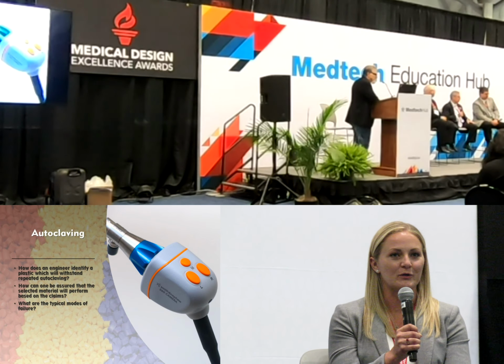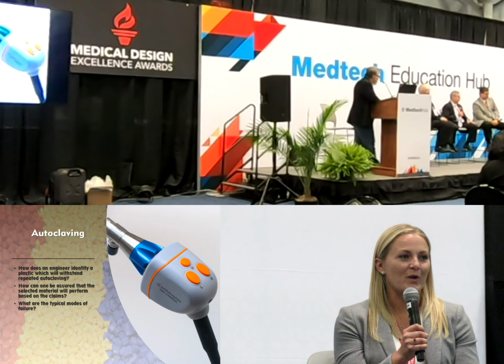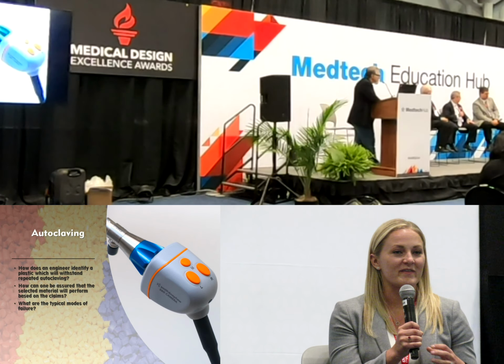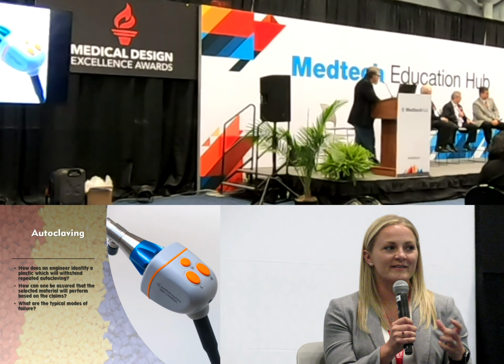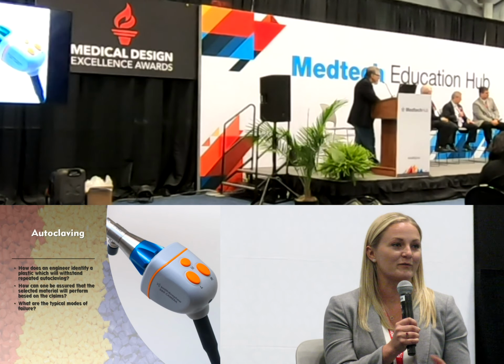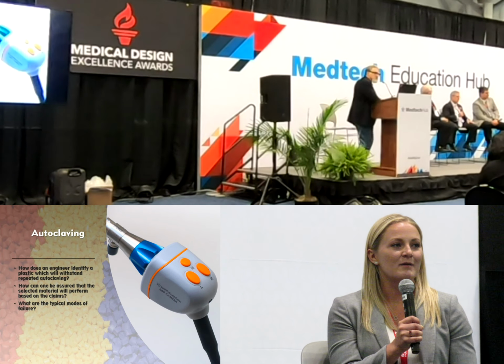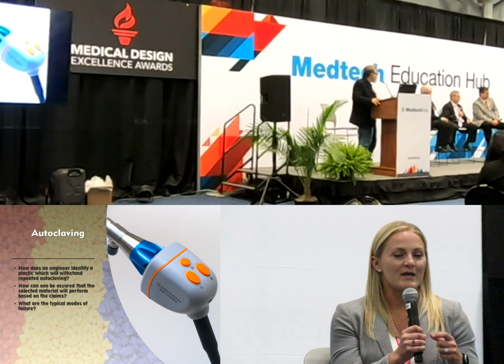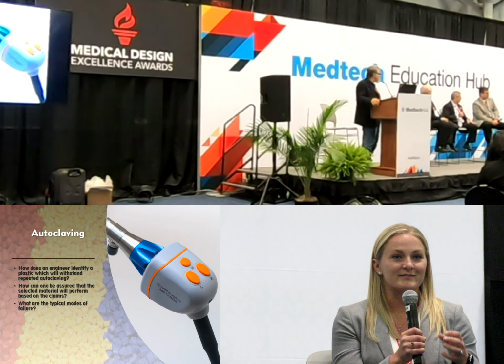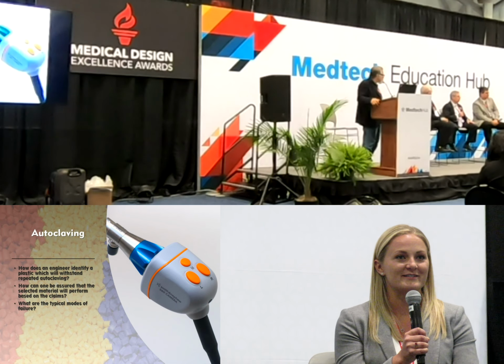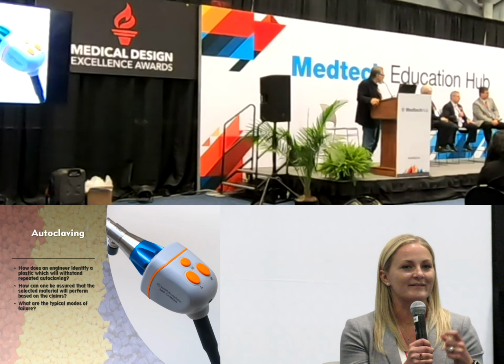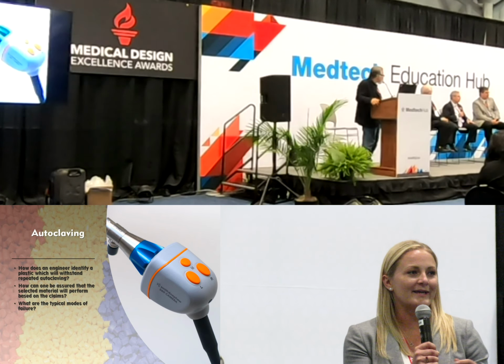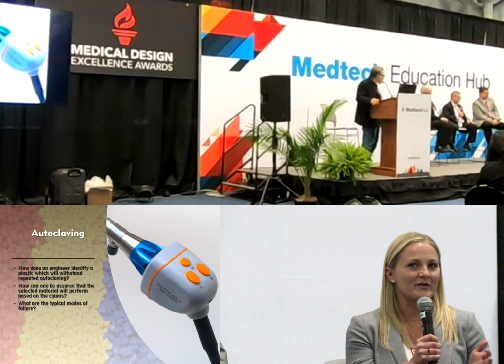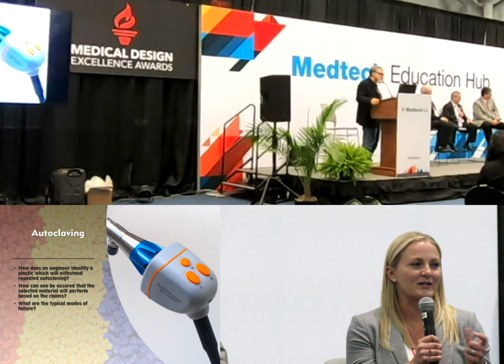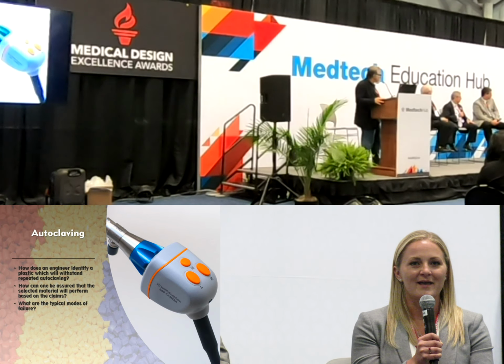A customer had come to us with a large metal insert, and they selected a material that is suitable for repeated autoclave cycles, but due to the CTE differences between the metal insert and the plastic and some stress concentrations in the design, they were getting failure cracking in the same spot every time. So again, it's important to keep in mind what are the other variables that are going to come into contact with that part in the application, as it's not just selecting a material that's suitable for autoclave.